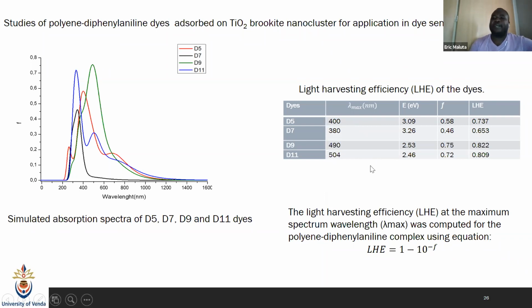And from the table, it's clear that the light harvesting efficiency for this type of the polyene diphenylamine dyes is more than 65%, and these are the natural dyes. That shows that the natural dyes give us an advantage. That will be seen when I'm talking about the inorganic dyes, the ruthenium one, which is coming. But the organic dyes now show an advantage because their light harvesting efficiency is high, which is one of the advantages of using the natural, the organic dyes.